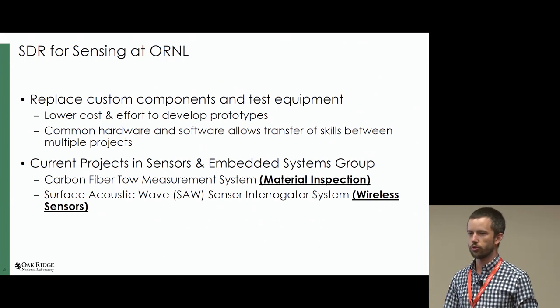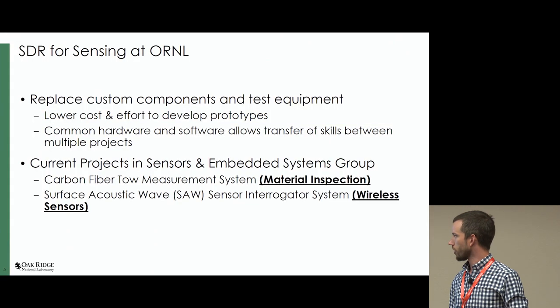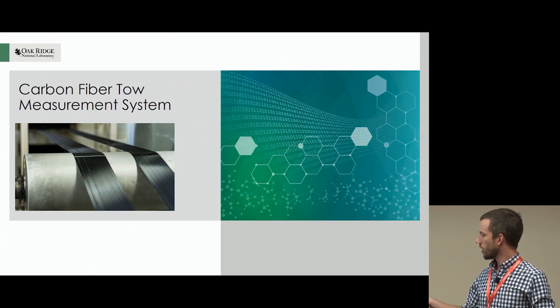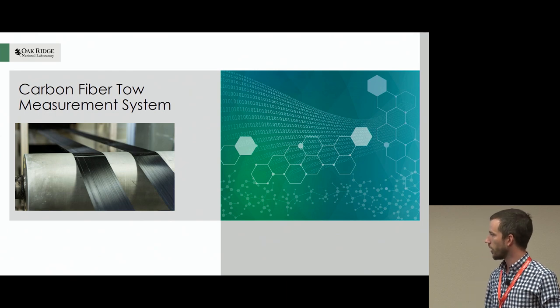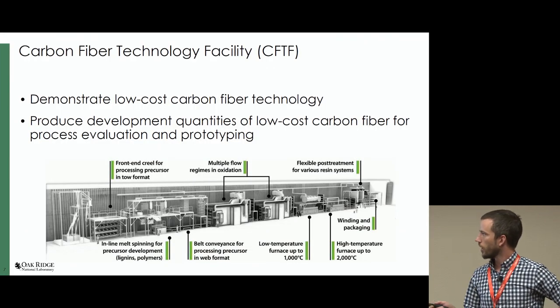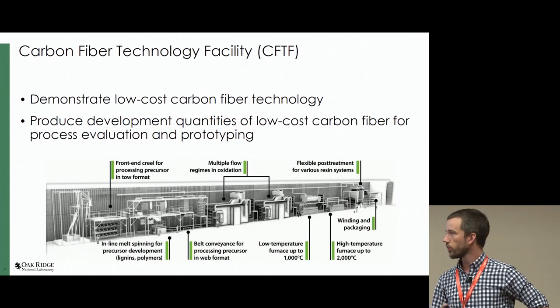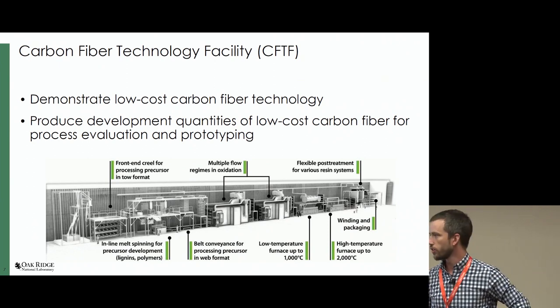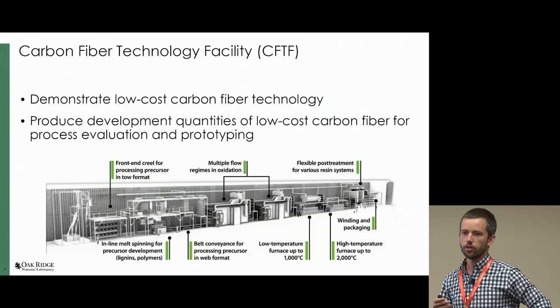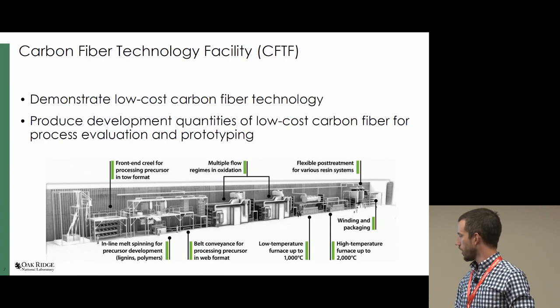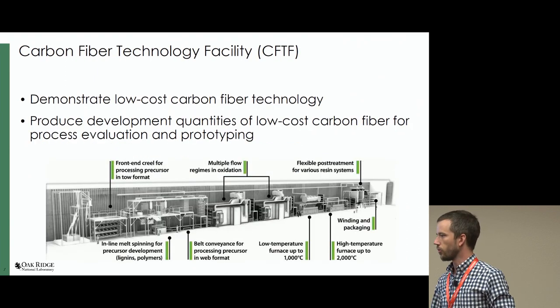One project is a carbon fiber measurement system where we're trying to infer properties of the carbon fiber. The other is on surface acoustic wave sensors for wireless sensing. At Oak Ridge National Labs, we have a facility called the Carbon Fiber Technology Facility. Its purpose is to demonstrate low-cost carbon fiber conversion methods using textiles as a precursor — like a polyacrylonitrile that looks almost like sheets of white cotton at the beginning. It goes through about a 100-yard processing line with various thermal processes, and out the end we get carbon fiber.